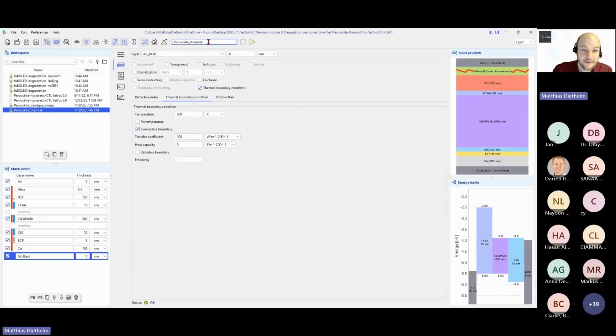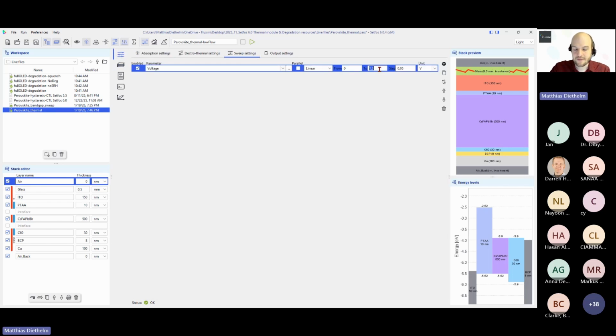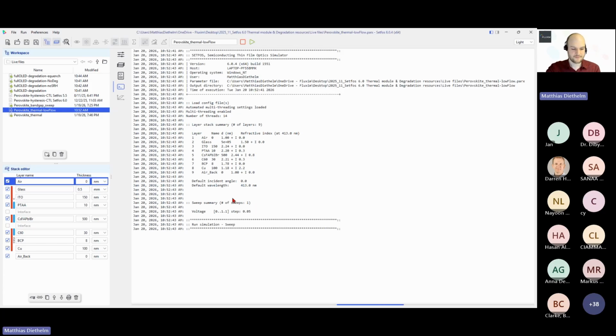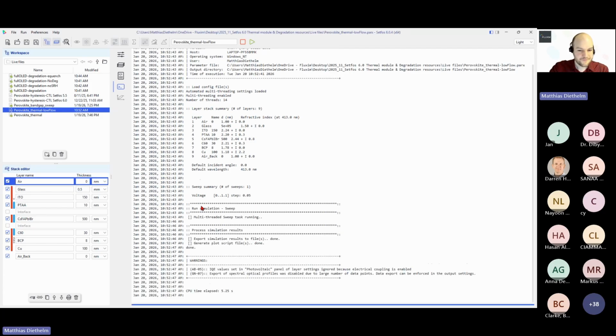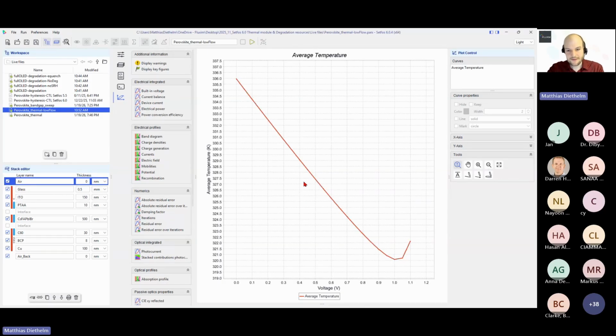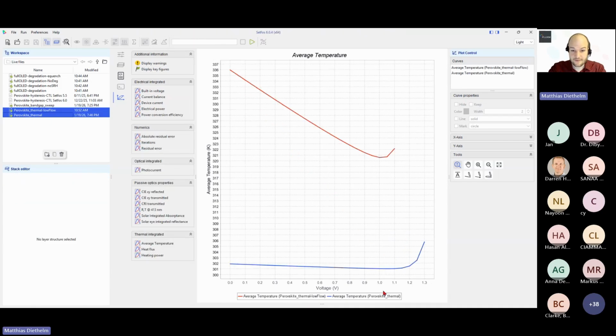So if we want to have a look into how the temperature changes if we set a parameter which represents no airflow at all on both sides, then we can run this example, and I have to put here the voltage sweep to only 1.1 volt, otherwise the simulation takes some minutes, which we can't do now in the live view. So with nearly no airflow, you can see here that the temperature effect is now quite drastic compared to the case if we have very strong airflow. So with this model, you can look into this. You could now look into what's happening if we go towards 85 degrees.